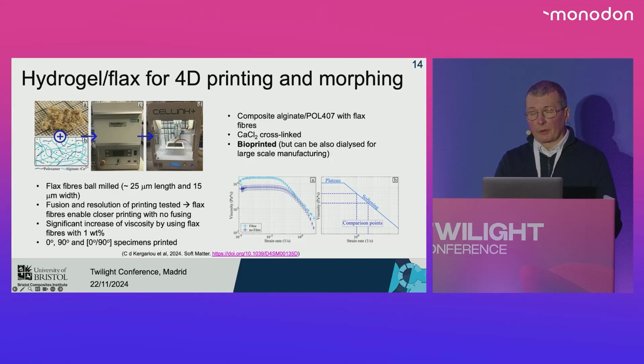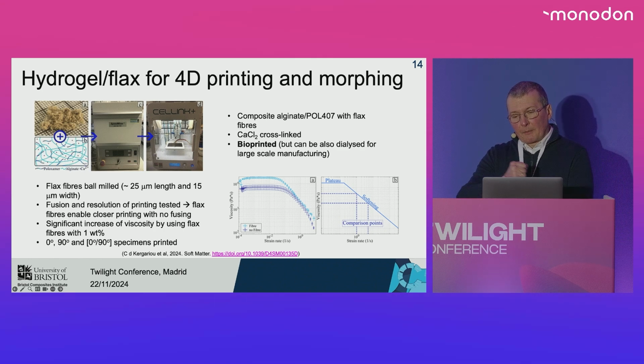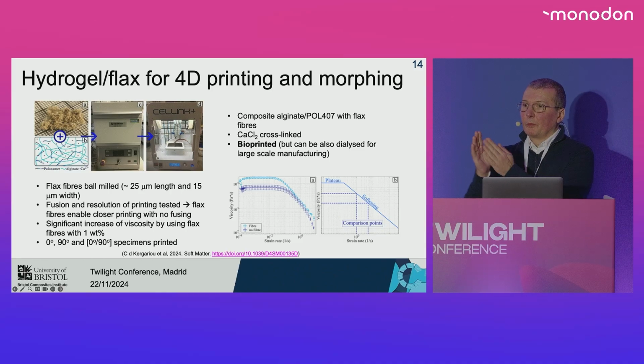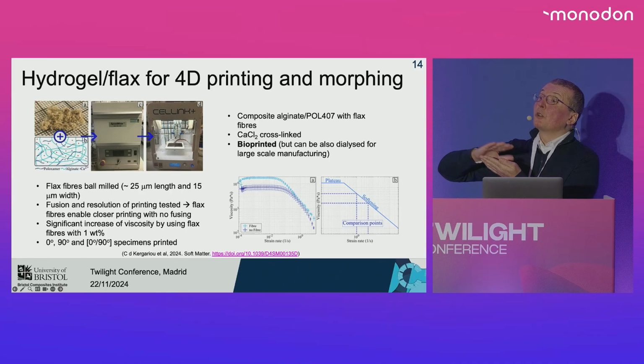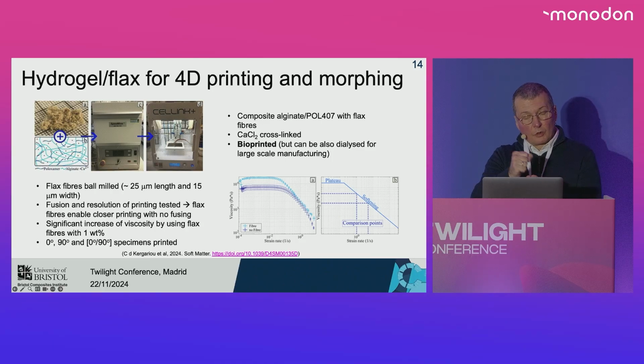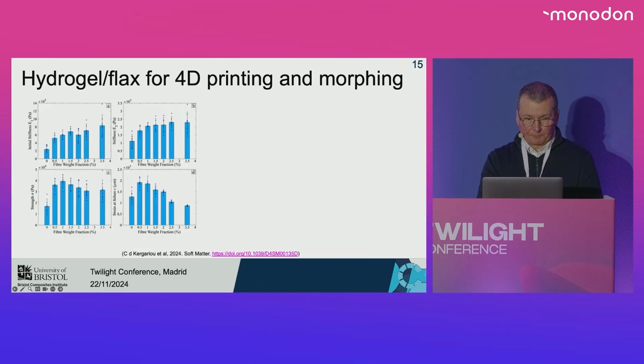but this happens with flax fibers up to 1% of weight fraction. And the same types of stacking sequences that we have used with the previous types of load-bearing hygromorphs have been used also to manufacture samples here. What we have observed first is you have a general increase of stiffness with the increase of the weight fraction. This is expected, but because of clustering reasons, the best tensile strength is always around 1% of weight fraction.